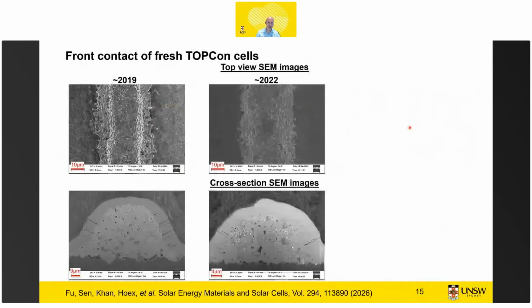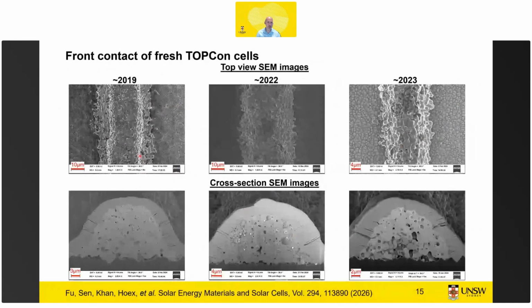If we then look at the cross-sectional SEM images and in the top view, we saw that there were some big changes. So there was a lot more metal used in 2019. Of course, we see this reduction in silver usage, so the lines are getting narrower, which increases the surface to volume ratio, which makes the cells a bit more sensitive. But what we also saw is that the amount of aluminium being used in the cells was increasing. And we saw that after stress testing, this aluminium was fully reacted, and that resulted in also etching at the interface, and that was the main root cause for this failure.